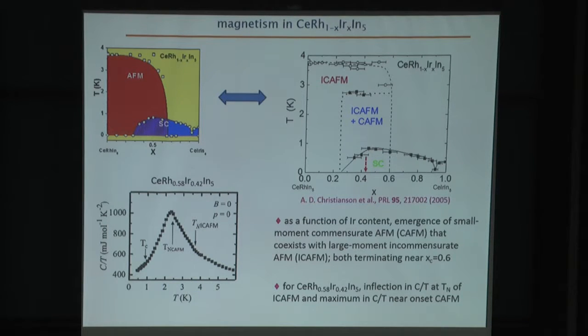So what we've decided to do is we've picked a sample that has 42% iridium. So that places it in this phase diagram at about this position here. So at this position, we have magnetism and superconductivity, but we know from neutron diffraction that this magnetism, in fact, this area in this phase diagram is rather complex in general. So if we cool a sample down at this composition of 42% iridium, it first enters a large moment incommensurate antiferromagnetic state, which is the same incommensurate magnetism that's found in pure cerium rhodium indium 5.